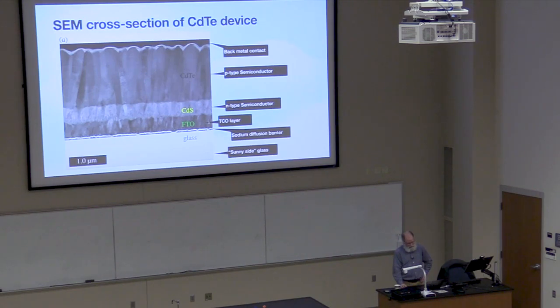Down here you can see this TCO layer. There is a thin tin oxide here, this little dark layer, and then this little white layer, that's silica. The idea of that layer is the glass has a lot of sodium in it. This little silica layer prevents that sodium from diffusing into the cell during processing or during the lifetime. So there are other things going on there too. And just to show the 1 micron bar here, this whole thickness is maybe 3 microns. A human hair is about 70 microns, so this is like 5% the thickness of a human hair on a piece of glass.